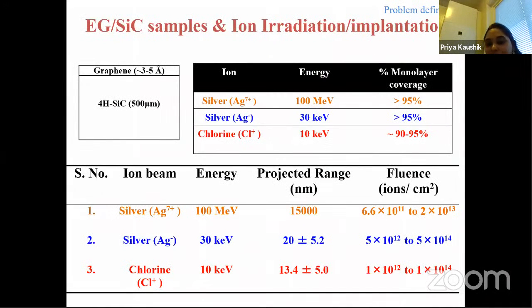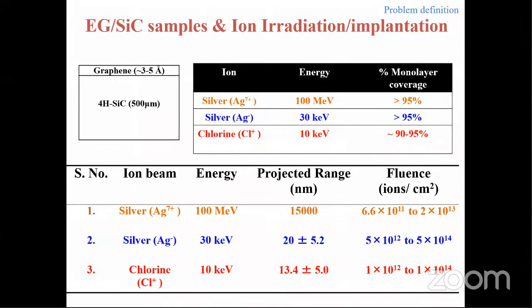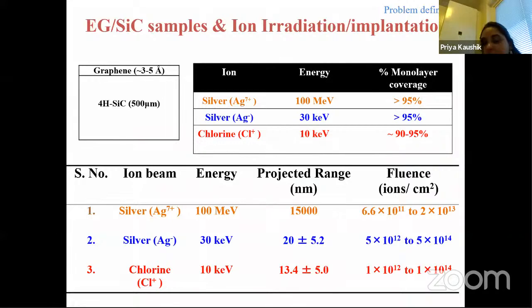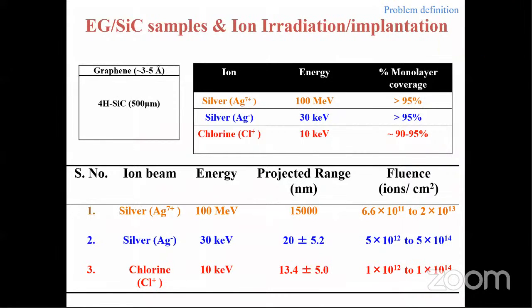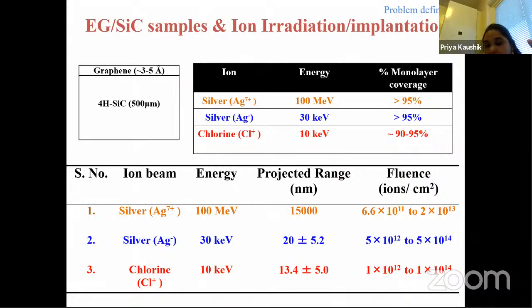This is just a glimpse of what we have done until now. We have used silver 100 MeV, silver 30 keV, and chlorine 10 keV ions. And with these particular ions, the projected range is 15,000 with 100 MeV. With 30 keV, we have used 20 nanometers. With 10 keV, we have used 13 nanometers.